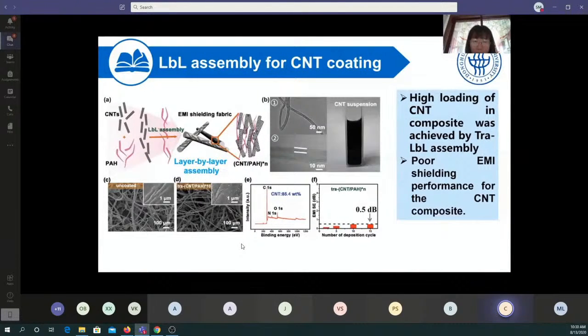In this way, we use a layer-by-layer assembly for CNT coatings. Here, we use CNT and PAH as building blocks for EMI shielding fabrics, and the obtained fabrics have a high CNT content, which reached 85.4%. However, the EMI shielding efficiency of the fabric only reached 0.5 dB, so the high-content CNT only resulted in poor EMI shielding performance of the fabric. We also checked the conductivity of the materials. The conductivity of the fabric is low. Even after 50 cycles of assembly, the conductivity was only 0.4 siemens per meter.